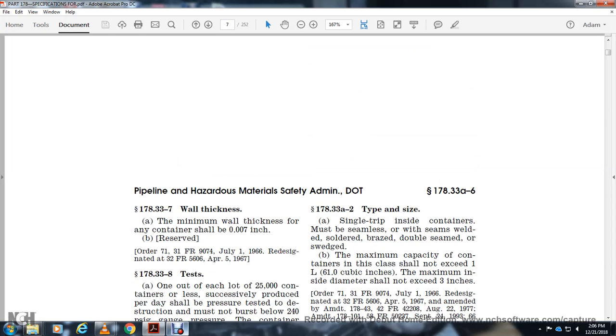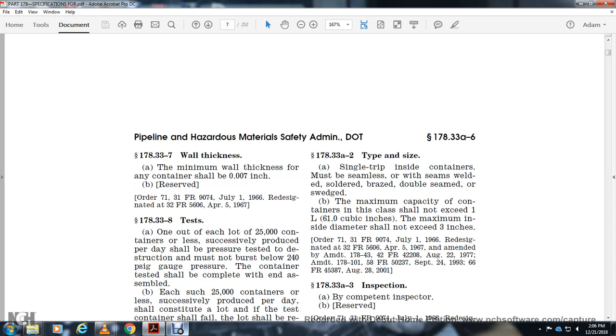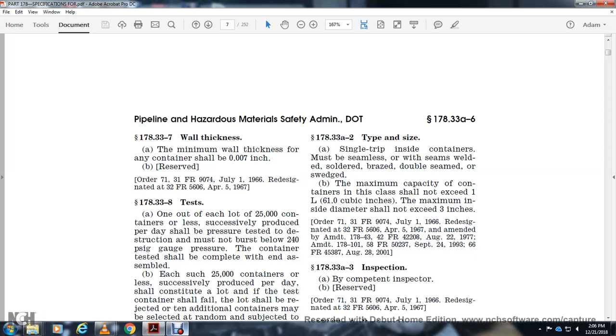178.33-7, wall thickness. Minimum wall thickness for any container, 7,000ths of an inch. 178.33-8, test. One out of each lot of 25,000 containers or less successively produced per day shall be pressure tested. The container may not burst below 240 psi gauge. The container test should be complete with the end assembly.